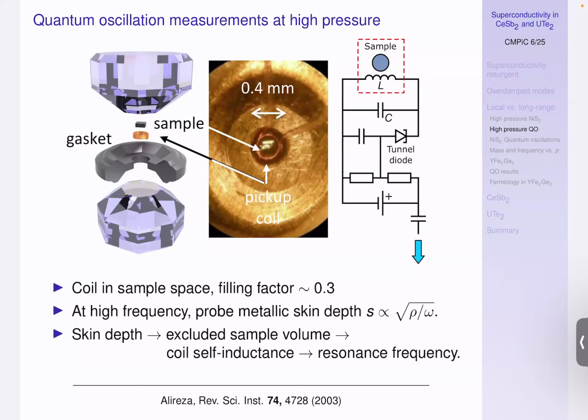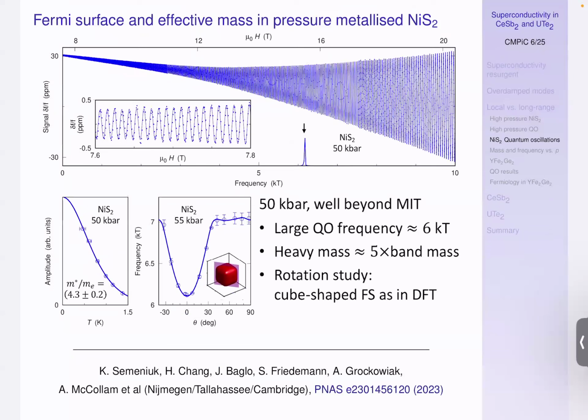The point is, we measure the resonance frequency of an LC circuit, and that depends on the properties of the sample. In particular, it depends strongly on the resistance of the sample via the skin depth phenomenon that happens at high frequencies on such metallic samples. So you can deduce changes in the skin depth from changes in the frequency, which give you changes in the resistivity. And frequencies you can measure very accurately, a few hertz per 100 megahertz, so basically 1 in 10 to the 8 resolution, which you cannot get easily using straightforward four-point resistivity measurements. So it's actually quite a nice technique. It has a lot of pitfalls, but for seeing oscillations, it's very nice.